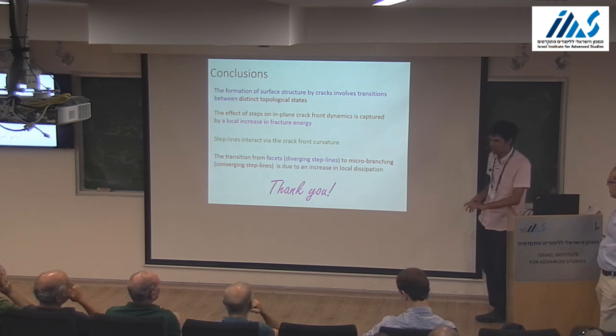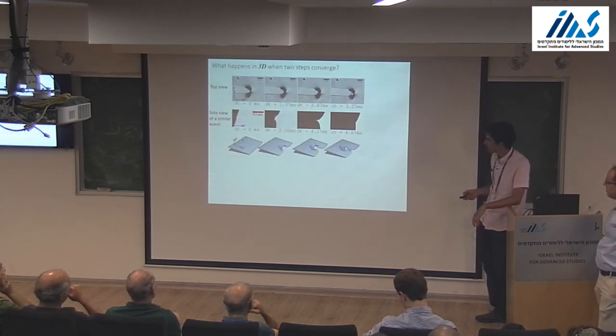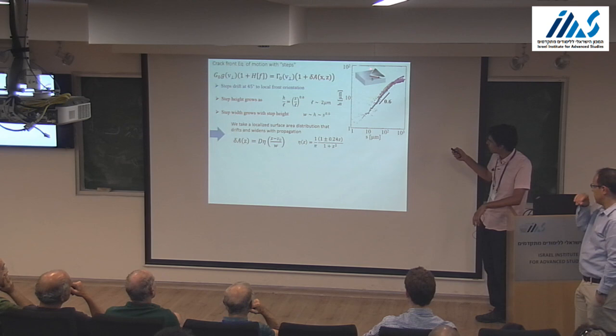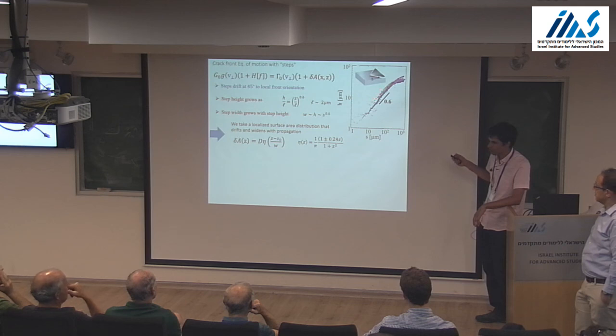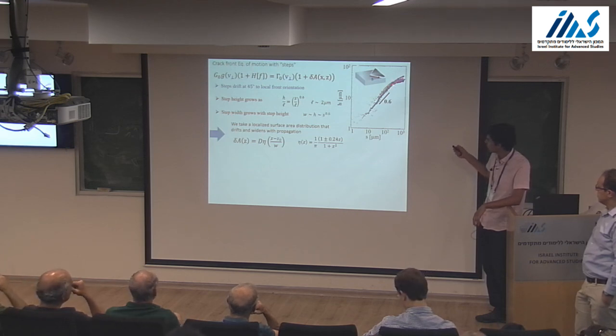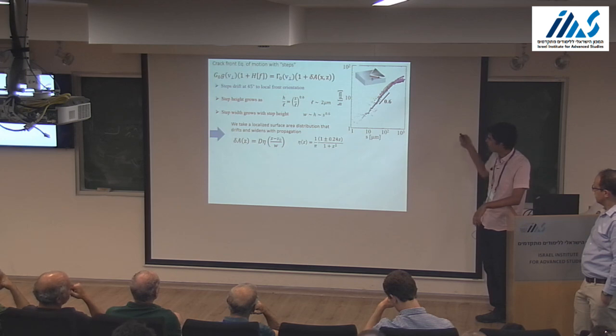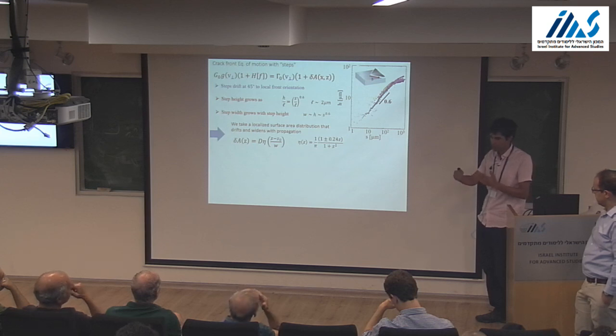So I think step growth is a bit of an involved process, but when we look at double nucleations like you see here, it seems that they grow without a scale, except this nucleation scale, and then at some point they saturate, or rather change the exponent, and we see that it happens when it comes within some distance from either the boundaries of the sample or other steps.